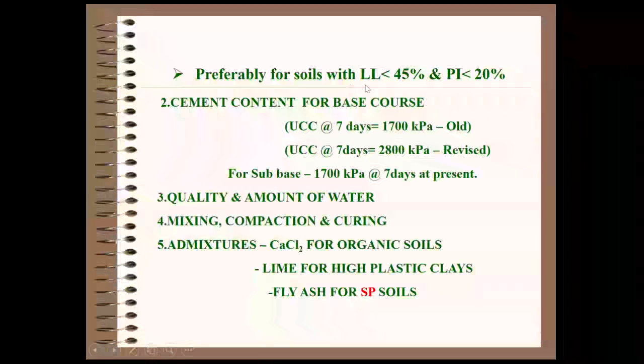These are some of the other guidelines. You see, liquid limit should be less than 45, plasticity index should be less than 20 for cement stabilization to be used. Then the required unconfined compressive strength with cement stabilization for different purposes is also given. Old code suggested 1700 kPa, that means 17 kg per centimeter square at 7 days curing period, but the revised code now increased this value to 28 kg per centimeter square or 2800 kPa at 7 days curing period.